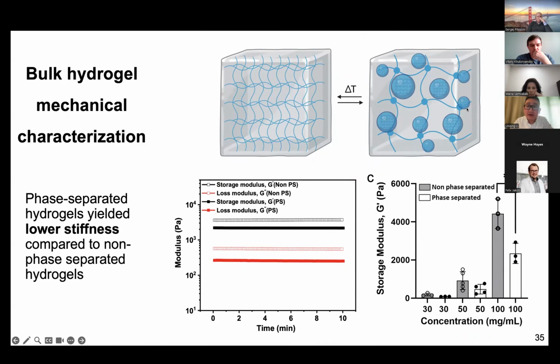In the solid squares here. So now, which makes us rethink the structure of the hydrogels: why do the phase separated gels have a lower modulus? If you think about the cross-linking density in the network, in the non-phase separated gels you have a relatively uniform distribution of cross-linking density, which gives you a higher modulus. But in the phase separated gels, you now have phase separated regions which are highly cross-linked. So you have regionally stiffer areas, but overall, because the chemical composition stays the same, you have a softer matrix, but locally I believe you have a higher stiffness region.